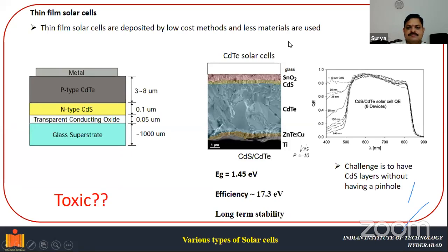One can deposit them by low cost methods and less materials are used. Like if you consider cadmium sulfide or cadmium telluride material, cadmium sulfide will be the n-type material, and cadmium telluride will be the p-type material. And at the bottom, you will have transparent conducting oxide, and all these things will be deposited on top of a glass substrate, and at the top you will have a metal electrode to close the circuit.